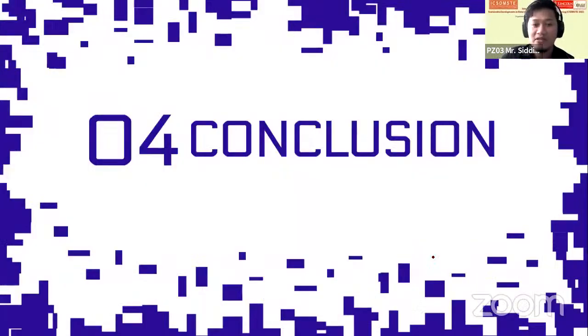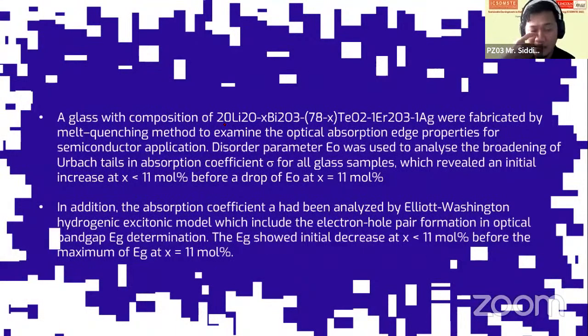So in conclusion, you can see from here, first we make our glass samples and examine their optical absorption properties, and then we calculate the disorderness parameter for all glass samples. After that, we analyze our absorption coefficient data by using the Elliott-Wannier model, because this model considers the electron-hole formation, the formation of excitons, and also the exciton-phonon coupling in our optical band gap determination. So we can get the result. That's the end of my presentation. Thank you.